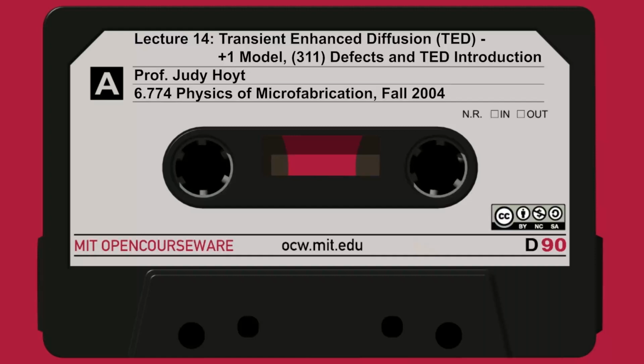What it's believed to be is a ribbon-like defect where this arrow points along 311, and the long section into the page lies along 110. It is a whole series of dimers, little silicon clusters, in this defect. It may be 100 angstroms long, let's say 10 nanometers, and maybe 30 or so in this direction. So it's a little cluster of interstitials that has a particular orientation.